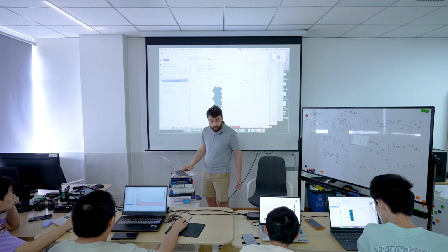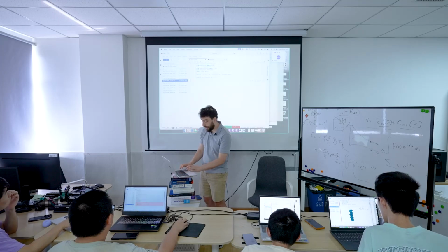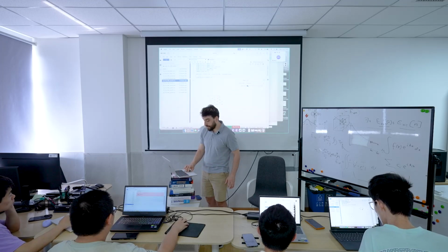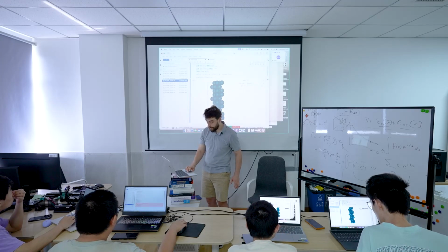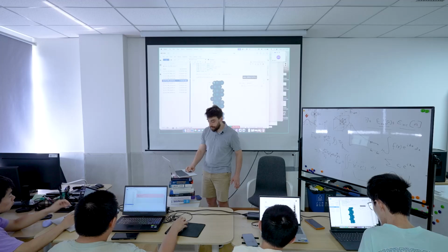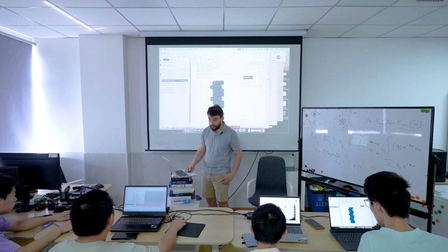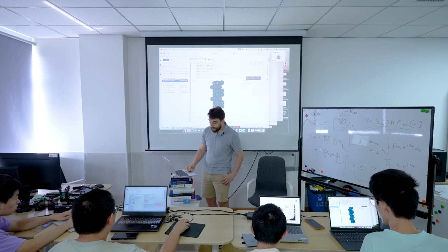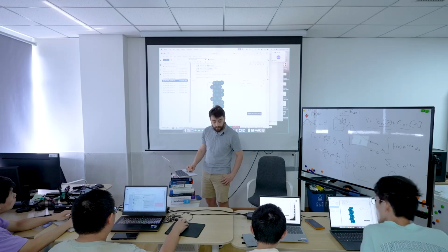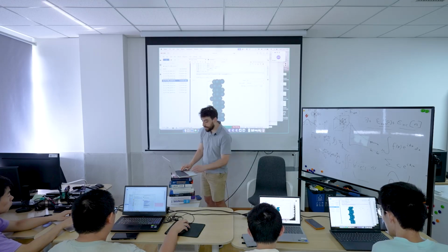If I make that smaller, you can see what the problem, the singular matrix, was. So if I just make it, say, 0.5, right, you can see in this case, now we have almost no vacuum gap. You see the atoms are right next to the edge of the cell. And because we have periodic boundary conditions, because we have a plane wave basis, these atoms are basically in the same positions as these atoms. So they're touching each other. Okay? So that's no good. Let's set it back to being about 5 Angstroms.